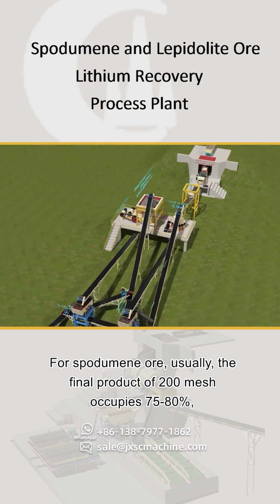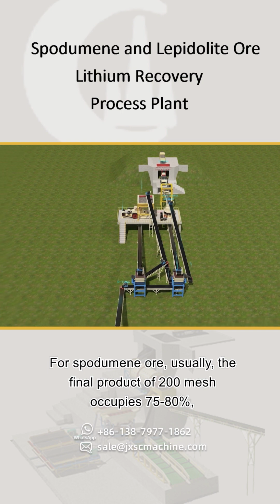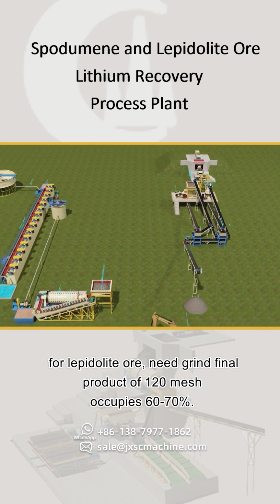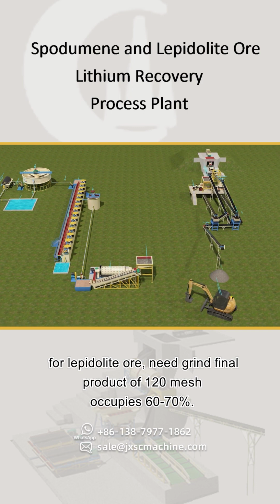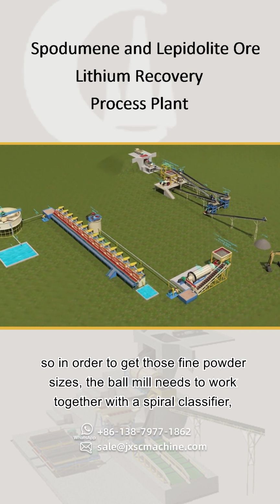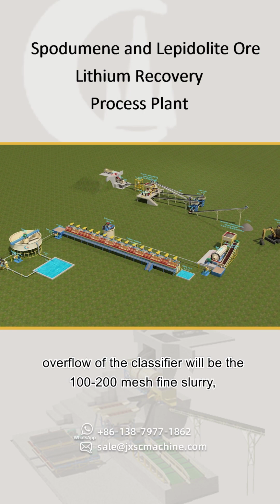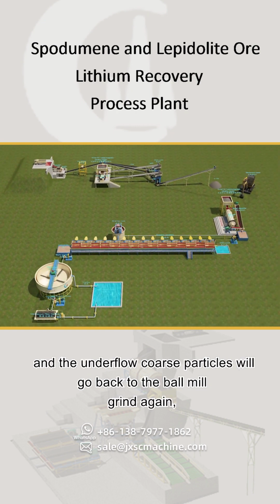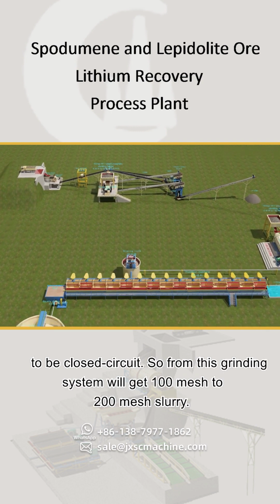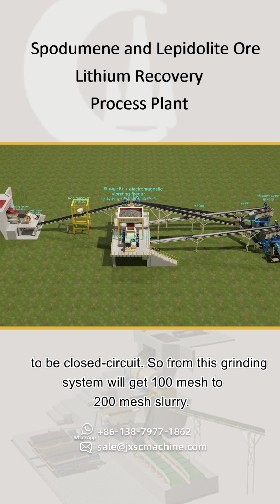For spodumene ore, usually the final product of 200 mesh occupies 75 to 80%. For lepidolite ore, need to grind the final product to 120 mesh occupying 60 to 70%. So in order to get those fine powder sizes, the ball mill needs to work together with a spiral classifier. Overflow of the classifier will be the 100 to 200 mesh fine slurry, and the underflow coarse particles will go back to the ball mill to grind again, to be a closed circuit. So from this grinding system we'll get 100 mesh to 200 mesh slurry.